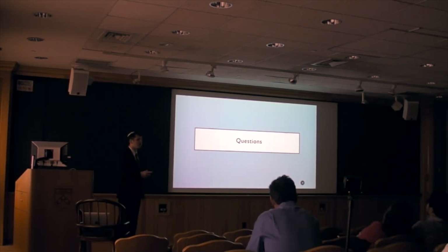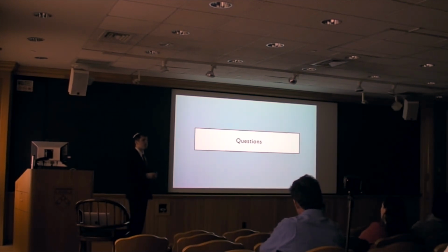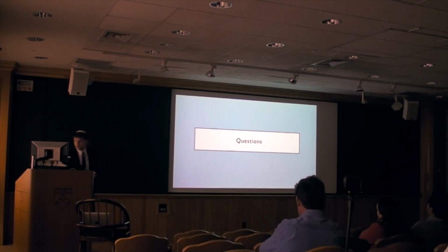So in regards to your hydrogen coverage and your Ni2P, is that significant in predicting the Gibbs free energy? Is that Gibbs free energy dependent on how many hydrogens you have on the surface, or is that calculated based on some equilibrium coverage? Sure. So yes, the binding energy in principle does depend on coverage. However, on this particular site, they bind so strongly and they're spatially isolated from one another at the nickel hollow site that the binding energy is pretty much equal at each site. And I can show you that if you can.